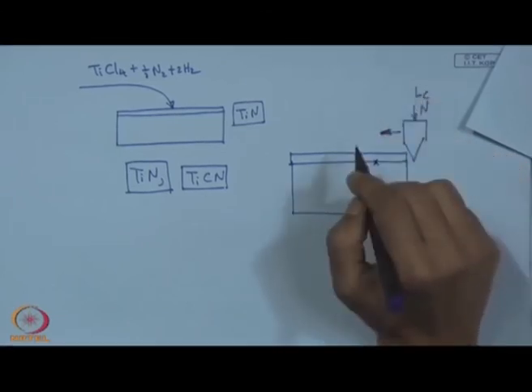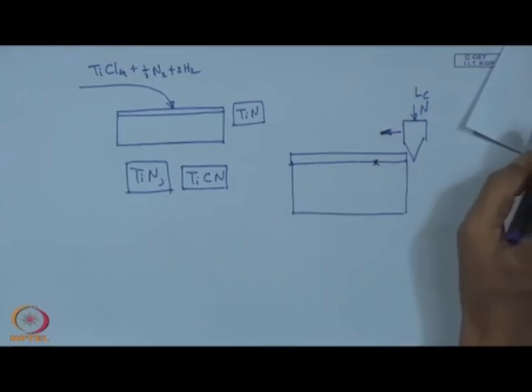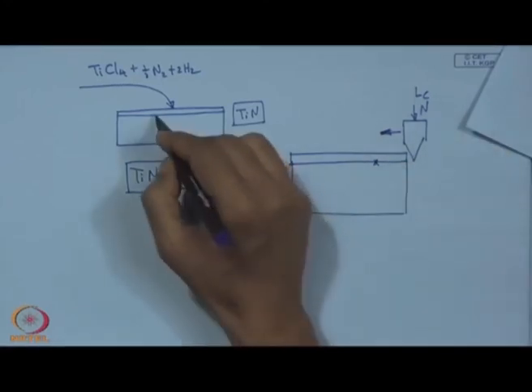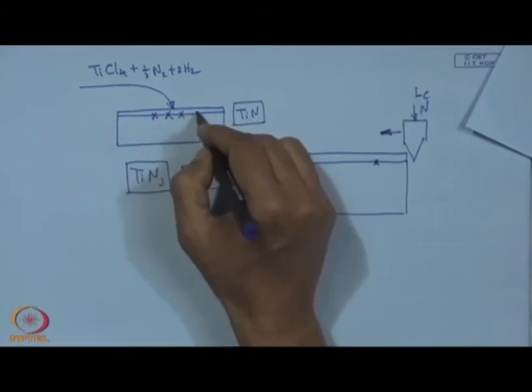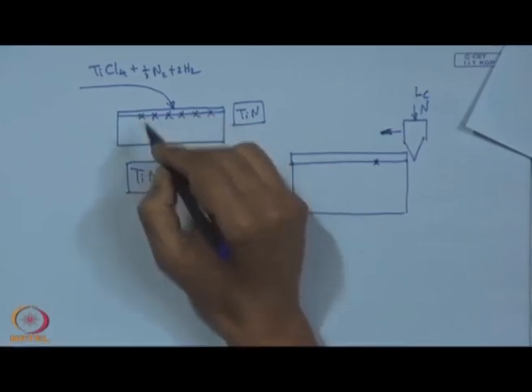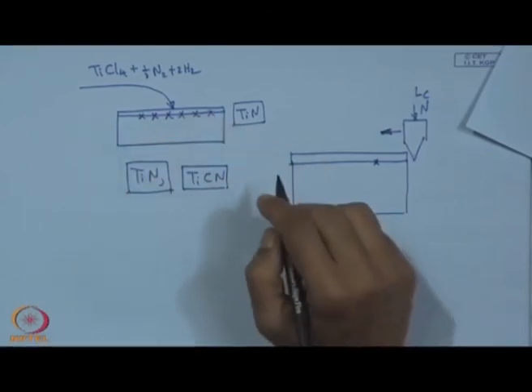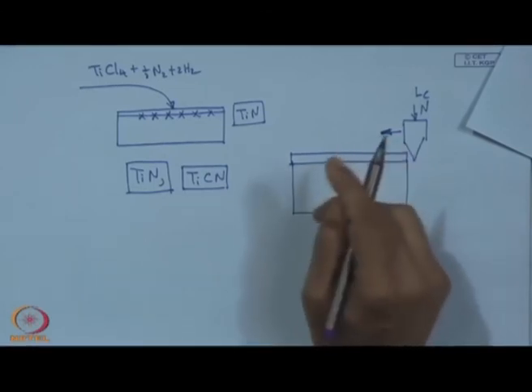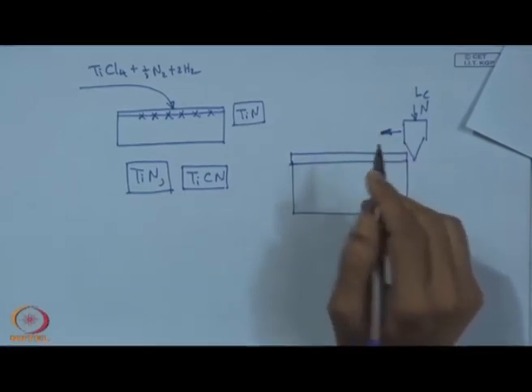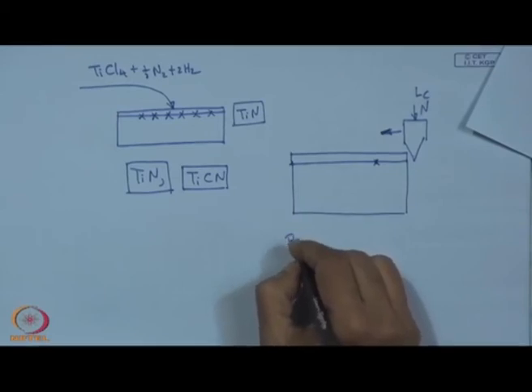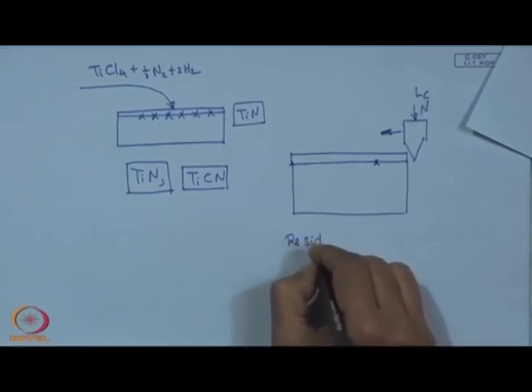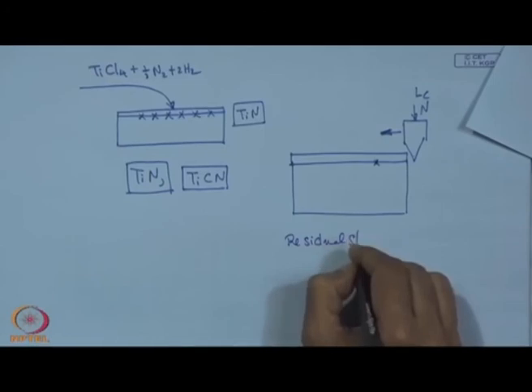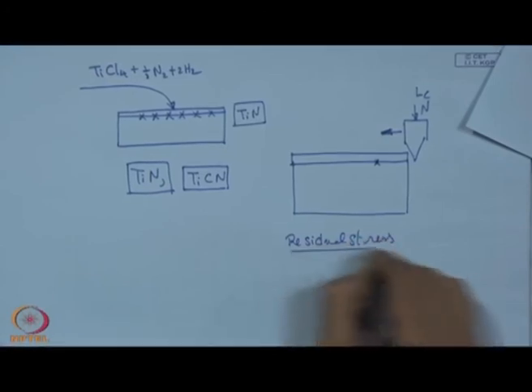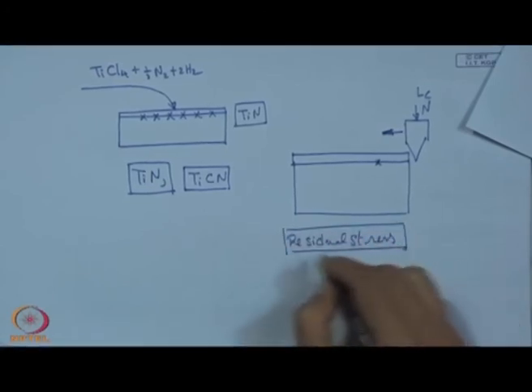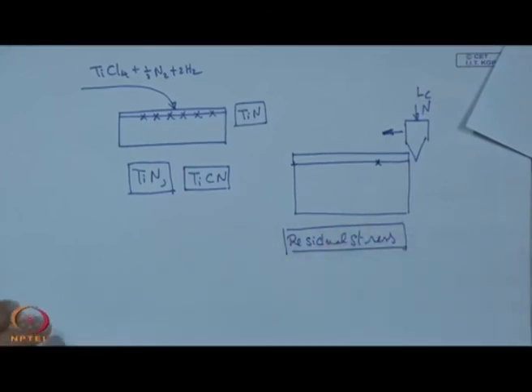So, this critical load has a rise because of this reaction, very strong adhesion, chemical attachment, but because of this high temperature, finally that is going to be offset or neutralized by the residual stress. Residual stress at this point. So, one has to also look into this while setting the temperature.